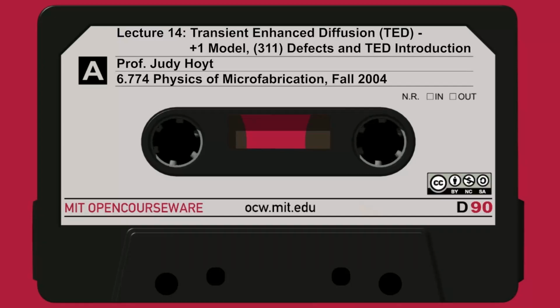So the TED is going to occur between this period of 0.1 seconds and 1,000 seconds, depending on the temperature you're at, how long it takes to evaporate the 311s. During that period, when the supersaturation ratio is large, it's going to be some high number, could be a factor of 10, 100, 100,000, something like that, and uniform in depth. So as the 311 defects, which have all been formed, now start evaporating and emitting interstitials, eventually they'll all evaporate away, and TED will be over. But for some period, they'll be evaporating, holding Ci over Ci star very high, and therefore holding the boron diffusivity very high.